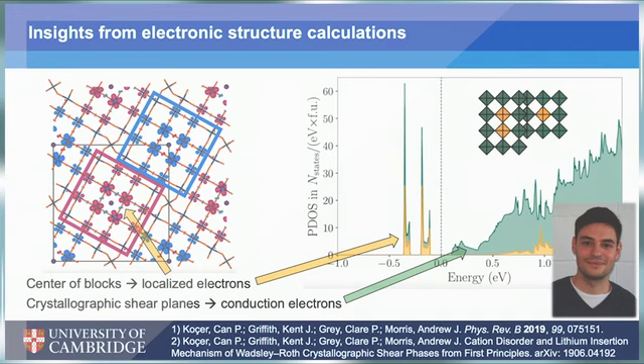And so what we found through these electronic structure calculations is that in these crystallographic shear structures, there are sort of 2 different types of metal cations. There are the ones that are in the center of the blocks, and there are the ones that are along the crystallographic shear planes. And what we find is that the ones in the center of the blocks sort of hold electrons more tightly and have localized behavior. And the ones along the shear planes have overlap that provides for metallic conductivity once we've lithiated these materials.